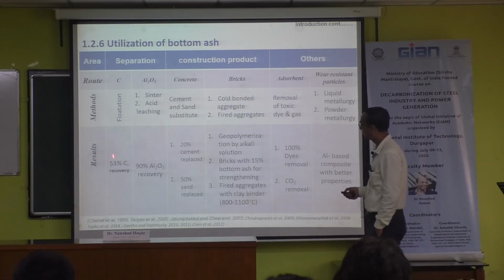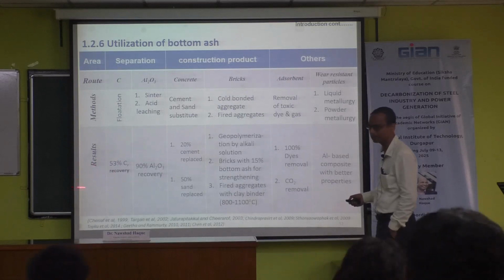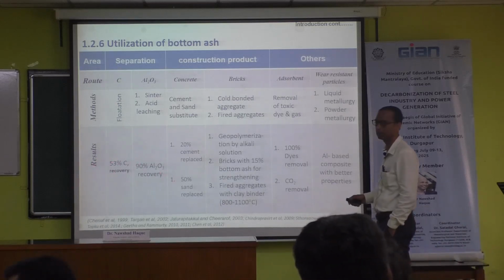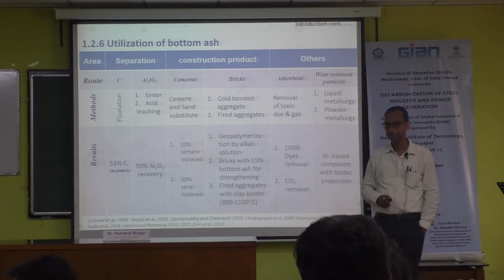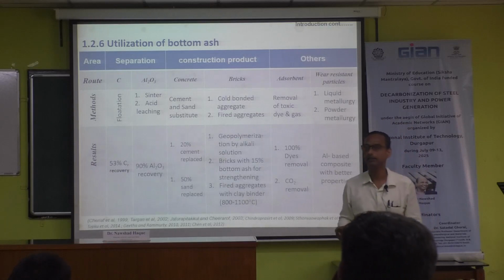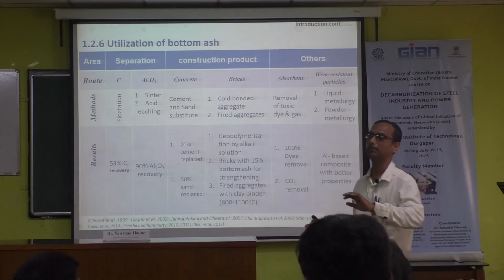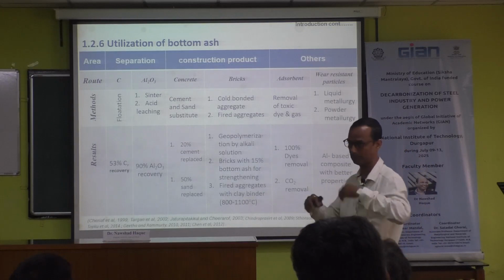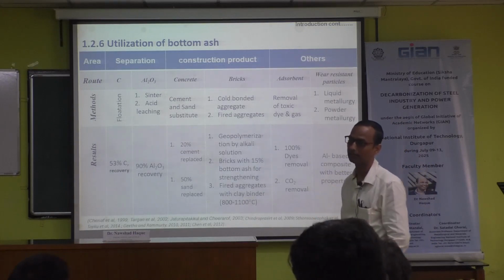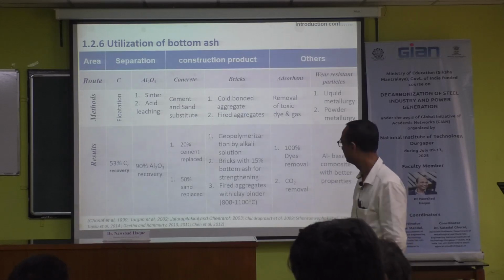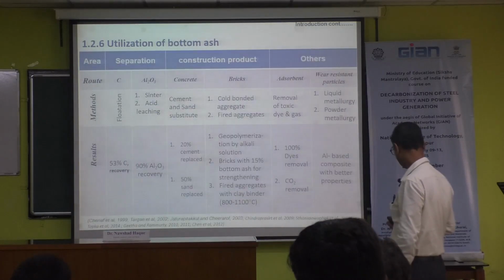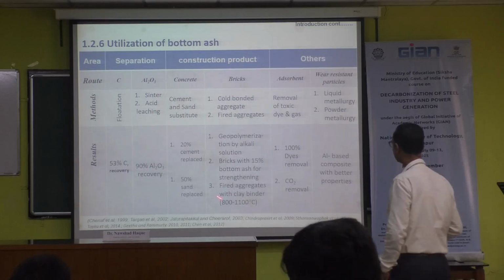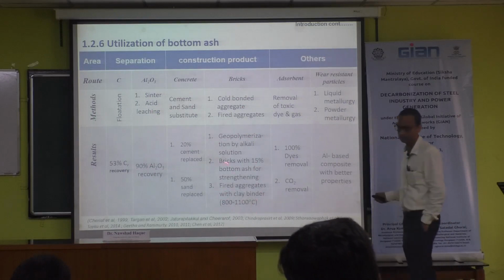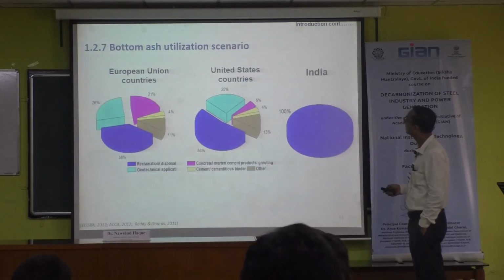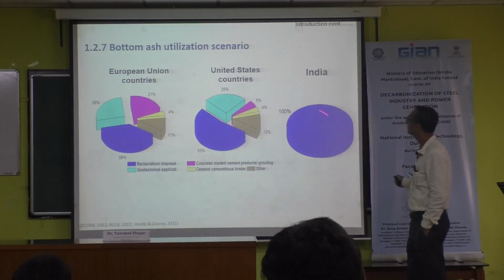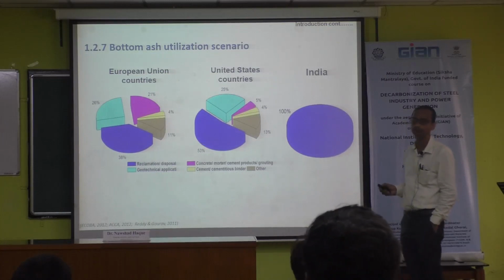And if you see the result, 53% carbon can be recovered from the bottom ash. That carbon has a calorific value, so people are doing this: after separation of the carbon, it is reverted back to the coal. It is mixed with the coal and we can inject it. And we have found some literature where people have also tried geopolymer and brick making.